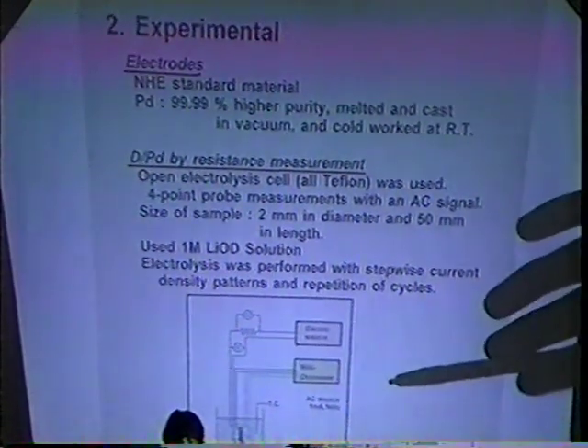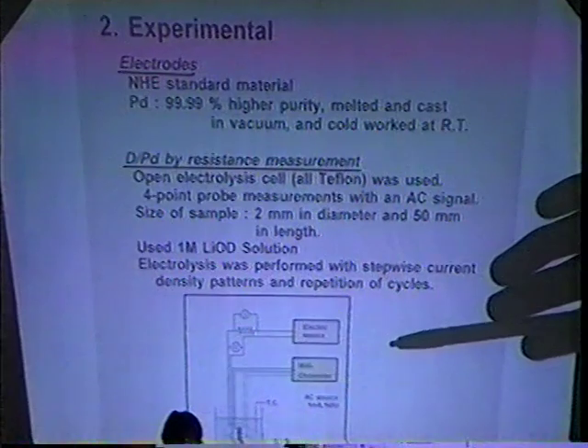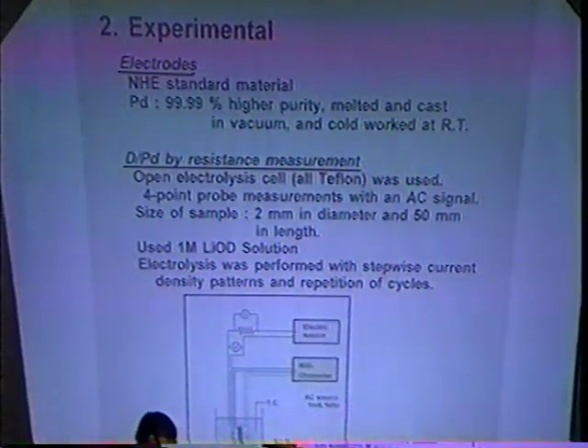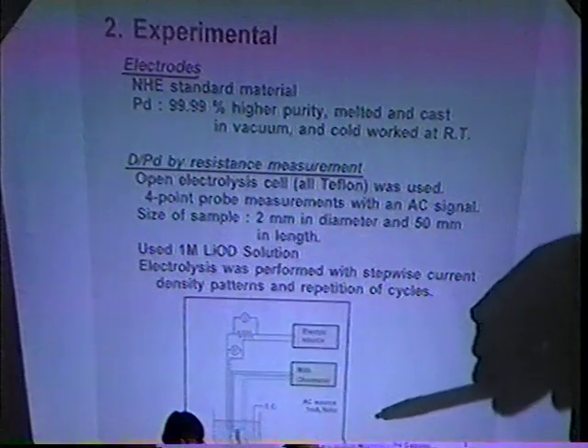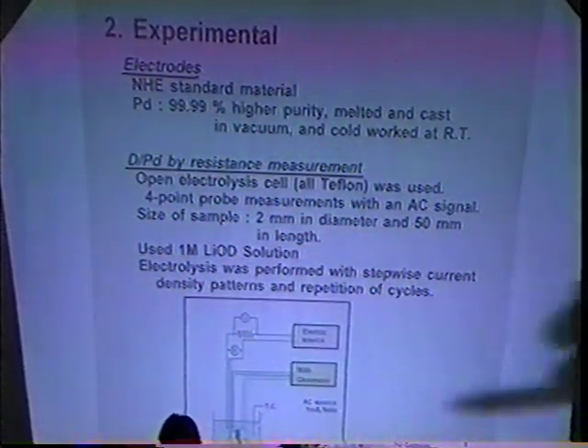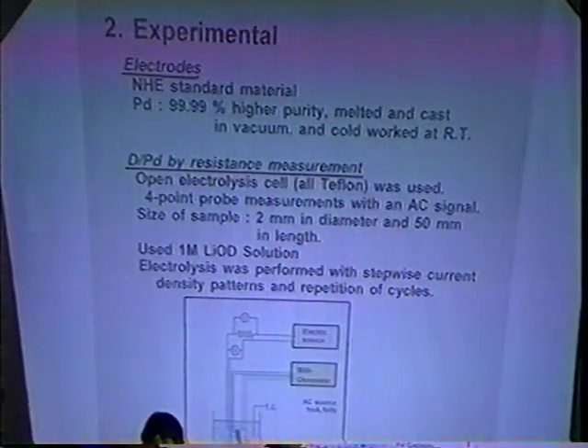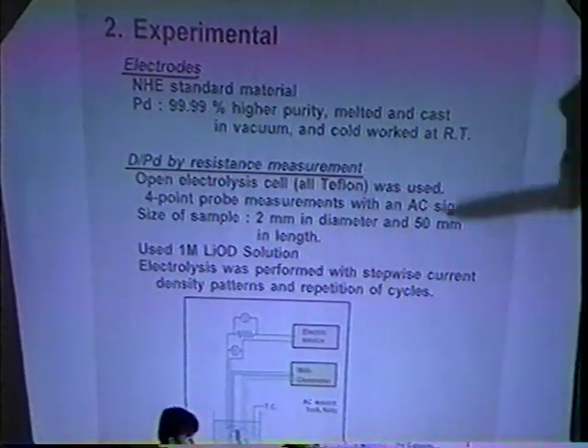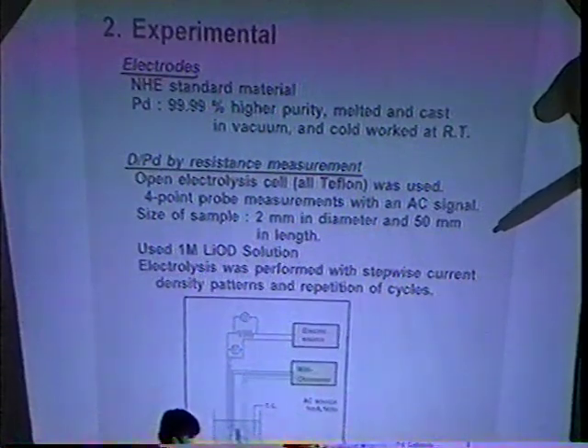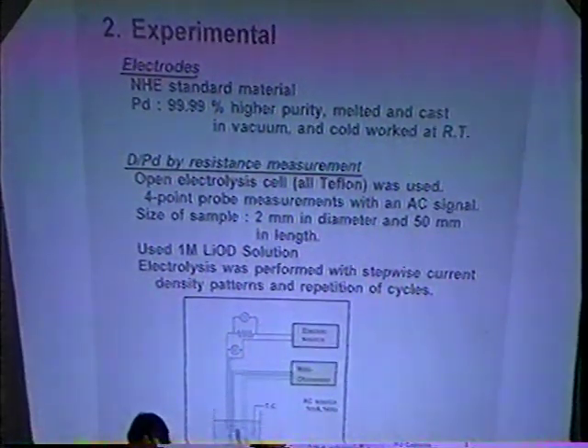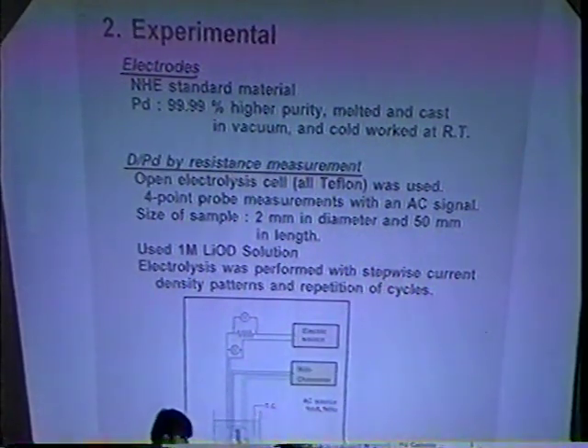Here is a schematic diagram of the electrolysis cell and system for resistance measurement used to calculate the ratio. The 4-point probe measurement is made with a 1 milliampere 1 kHz AC source. In all cases platinum wire or spot wire or palladium electrodes were used. The palladium electrodes were 2 mm in diameter and 50 mm in length.